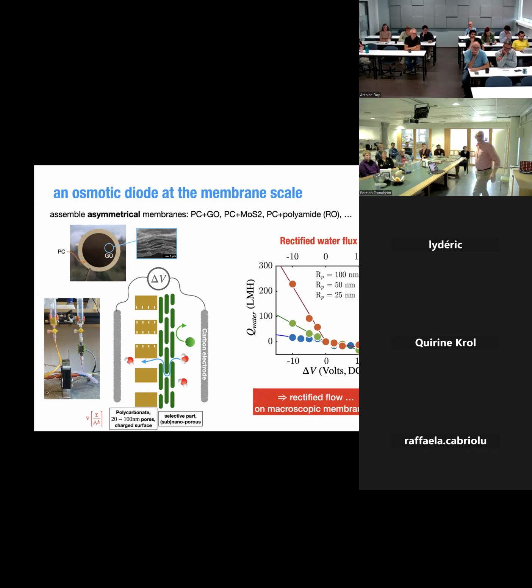And indeed, what you see is that the flux of water, in liters per square meter per hour, across the system versus the voltage is, in particular for these small but not too small nanopores, 25 nanometers, very asymmetric. And so that's a demonstration of this rectifier.